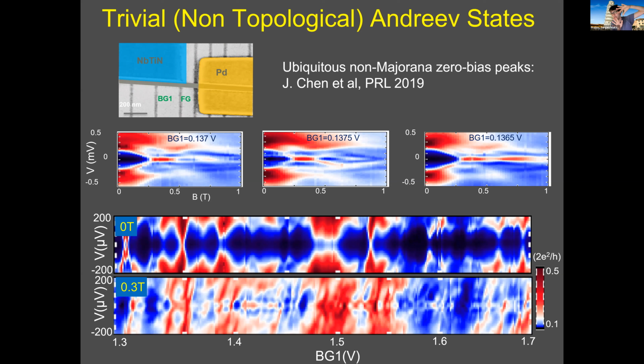You have to have a large amount of states all going to 0. So when it's a large bias window of conductance that kind of avalanches down to 0, touches, and then reopens, inside this crossing is nothing, and above the crossing there's a lot of current. That would be gap closing. This is just an Andreev bound state coming to 0 and then crossing and going through.